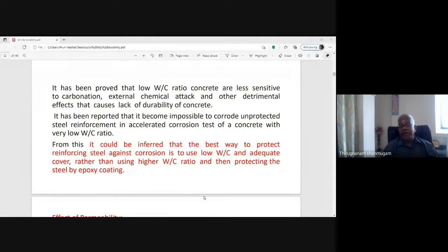But if you provide higher water cement ratio for workability considerations, it reduces the strength. Abrams' law shows that the compressive strength is inversely proportional to the water cement ratio. Whenever the water cement ratio is higher and higher, the strength is lower and lower. Not only the strength, the durability is also affected with higher water cement ratio. So if you adopt low water cement ratio, you need not give protection to the steel by epoxy coating or any other coating requirements. But if you adopt higher water cement ratio, then you have to protect the steel by epoxy or any other type of coating.